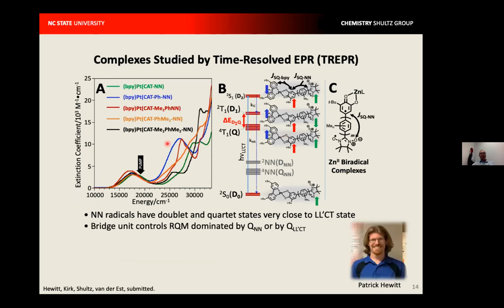So Patrick Hewitt has now made a couple dozen of these complexes, and in this series that I'll tell you about, we changed the bridge between the catecholate and the nitronyl nitroxide in the ground state, or the same bridge between the semiquinone and the nitronyl nitroxide in the excited state. So no bridge, paraphenylene, dimethyl paraphenylene, where the methyls are ortho to the catecholate, dimethyl paraphenylene, where the methyls are ortho to the nitronyl nitroxide, and then a paraphenylene that has 4 methyl groups on, so that the bridge is nearly orthogonal to the catecholate and the nitronyl nitroxide, which in turn shuts off conjugation between the catecholate and the nitronyl nitroxide radical in the ground state, or the semiquinone and the nitronyl nitroxide radical in the excited state.